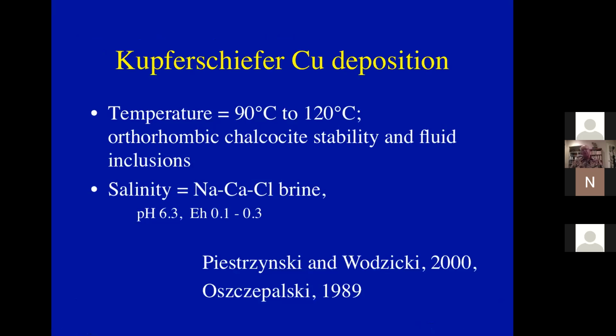So the Kupferschiefer copper deposition occurred at between 90 and 120 degrees centigrade. And that's identified by fluid inclusions and by the occurrence of orthorhombic chalcocite, which apparently is stable only at about 100 degrees centigrade. It was deposited from a highly chlorine-rich sodium calcium chloride brine at a pH of about 6.3, slightly acid, and at an Eh of 0.1 to 0.3. So deposited from a warm brine.